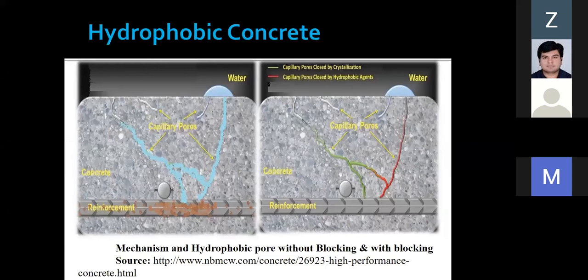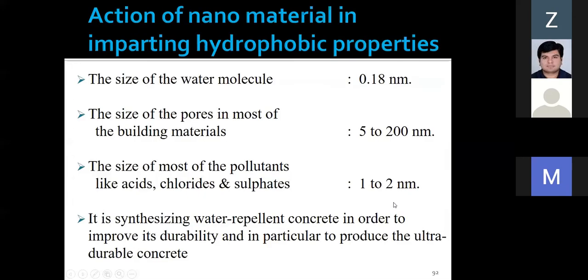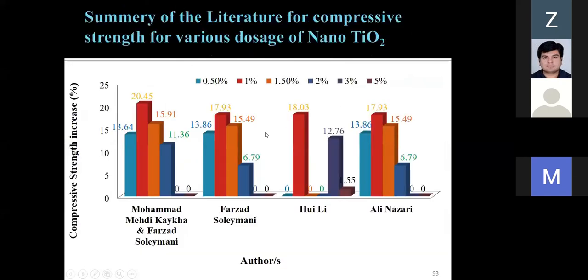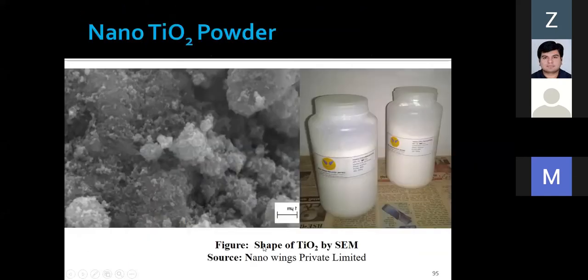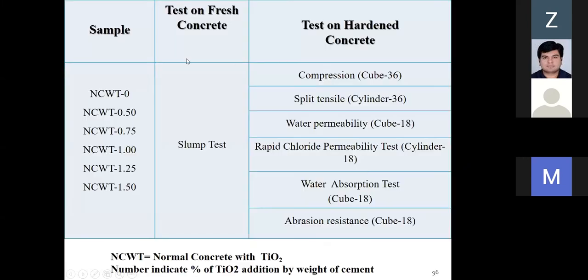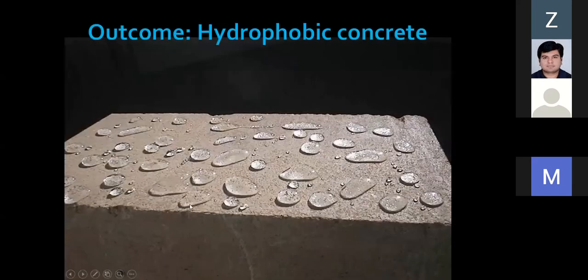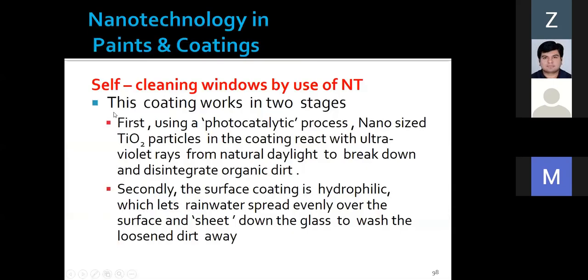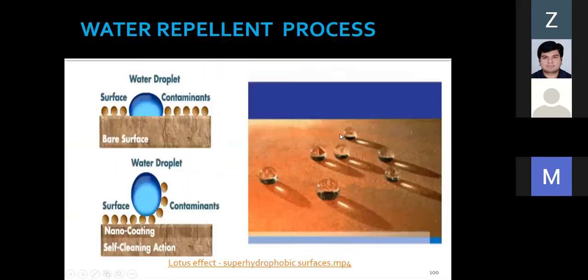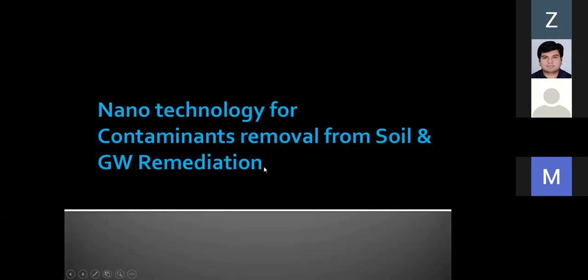So again, in our lab, we thought that if we make the surface of concrete itself hydrophobic, and these micro cracks and capillary pores are sealed, we can protect it. We tried that with nano titanium dioxide, we did the literature review, and at our lab we did this and we could get hydrophobic concrete. So self-cleaning windows, this is how it works, we already discussed.